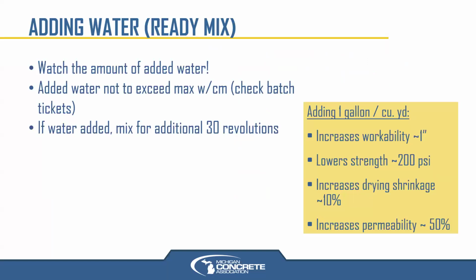Ready mix jobs, obviously we can adjust a truck. Many times, the truck is batched with a little bit of holdback water so that there is, quote unquote, room to adjust to bring the slump up or increase the water cement ratio. But definitely keep an eye on that. Don't exceed your max water cement ratio. Check weights on the batch tickets if those are printed on there. If water is added, it needs 30 revolutions to be fully mixed. We want that water to get through the full load of concrete, not just on the top where it's added. And remember, if you add water to concrete, 1 gallon per yard, it will increase the workability about 1 inch as far as slump measurement is concerned, but it will lower your strength approximately 200 psi.